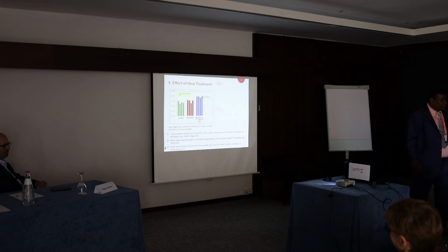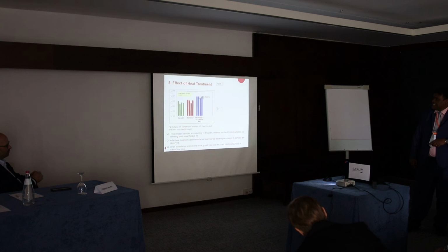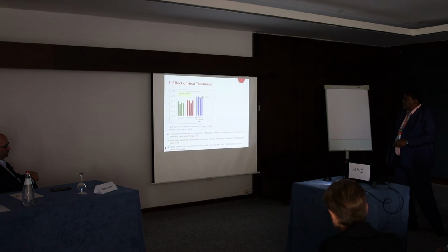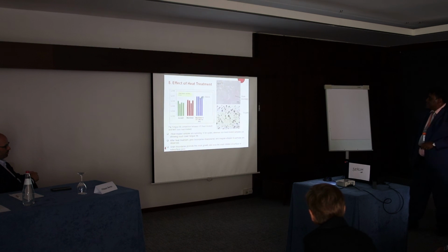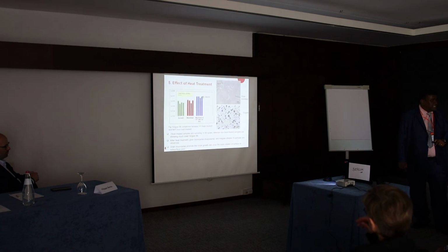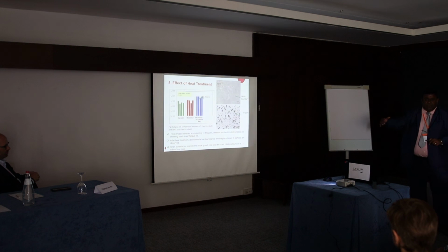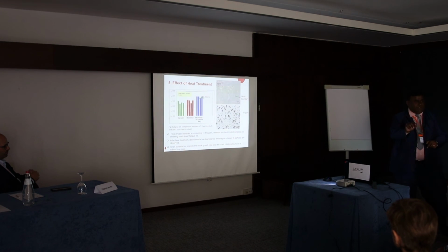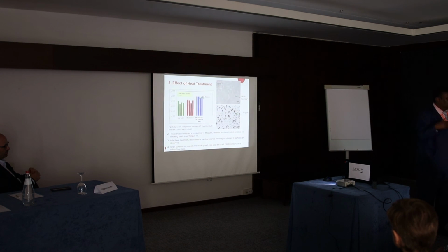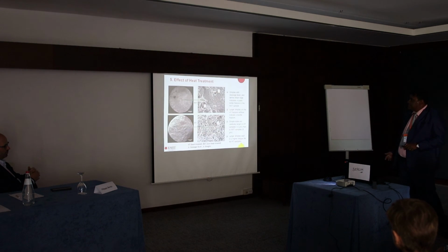Finally, I don't have much time, but the last thing is the heat treatment effect, which also shows that if you use heat treatment, you can get a significantly increased fatigue life compared to as-built and machined. You can see 500 hours of heat treatment gives you 10 times more fatigue life, because of what happens during heat treatment again: the grain boundary disappears and is filled with Si particles in this case. Grain boundaries promote crack nucleation. We remove them and fill them with foreign particles because of the heat treatment, and that raises the fatigue life. Again, it links to the fundamental microstructure and chemistry.